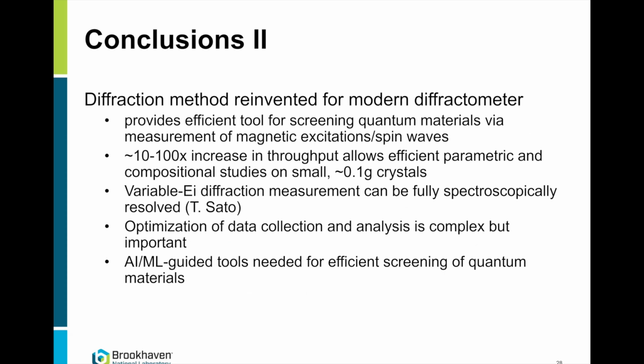This is my second part of conclusions. We have reinvented this diffraction method where we can measure spin waves on a modern diffractometer. And this measurement provides a very efficient tool for screening quantum materials because, again, this is amenable to a machine learning AI guided measurement where you have your small samples, you can just put them on a diffractometer one by one and then rotate them intelligently, screen them, and then refine the interaction parameters. It gives 1 to 2 orders of magnitude increase in throughput, which allows us to study much smaller crystals than typically studied by neutron spectroscopy.